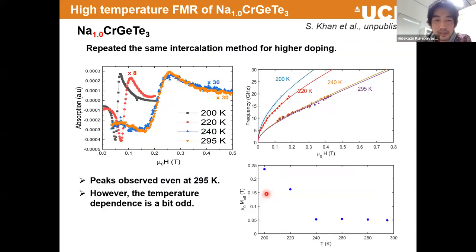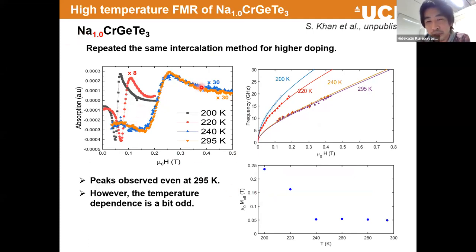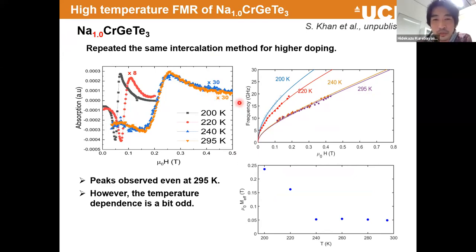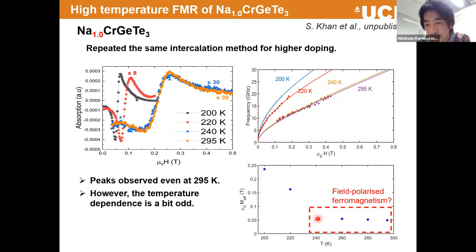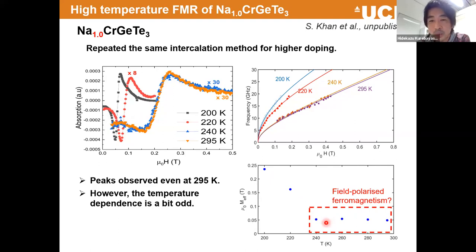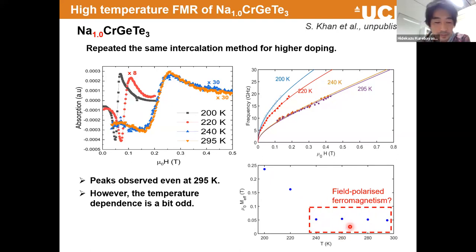When we dope the material with elements that create carriers, the arch-like behavior disappears and the curve goes down nearly to the origin — the typical easy-axis in-plane behavior. There are also additional spin-wave resonances we cannot yet explain, but it's interesting behavior. Temperature-dependent measurements show this FMR behavior persisting up to 240 K; at 250 K it disappears. In-plane versus out-of-plane rotation measurements confirm that in-plane is the easy axis. Our latest result shows we can sustain this magnetic resonance to near room temperature, though it may be a field-polarized paramagnetic order at the highest temperatures.